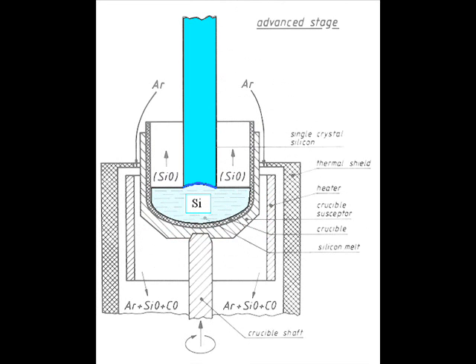During the process, the radial and lateral doping levels will be influenced as they will not stay constant. The concentration of impurities, especially the interstitial oxygen, may also change. In general, the concentration increases from head to tail. Crystal lattice defects will be present and may change in size and distribution.